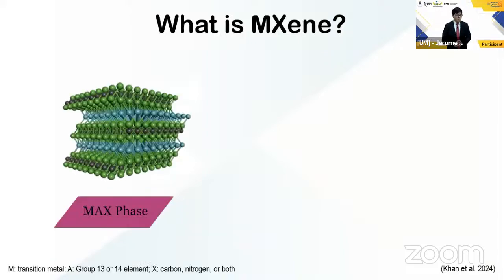MXene is a class of 2D nanomaterial, the same as graphene, that is made from a top-down approach from its precursor called MAX phase. MAX phase consists of alternating layers of Mn+1Xn and A, whereby the M is a transition metal element, the X a carbon or a nitrogen, and the A is usually a group 13 or 14 element, aluminium or silicon. So it consists of alternating layers of transition metal carbide or nitride and aluminium or silicon.